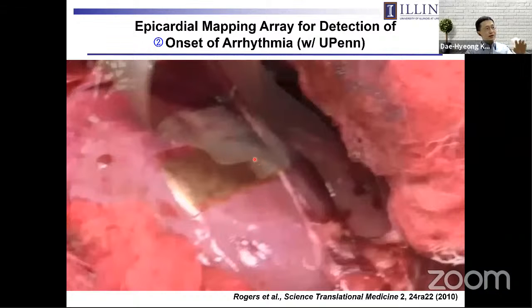So it could make very good conformal contact to this swine heart surface and could measure the propagation of the electrocardiogram with high resolution. Actually, this was the first work in the bioelectronic device in which we applied a silicon nanomembrane.